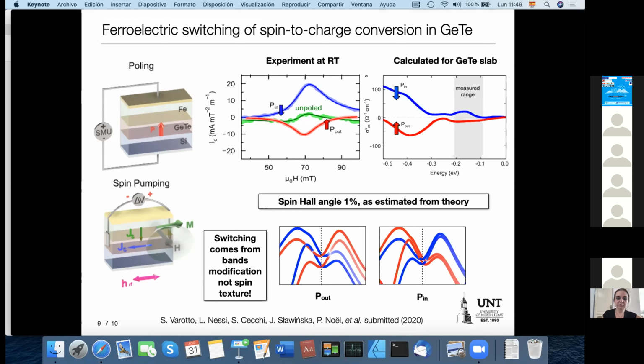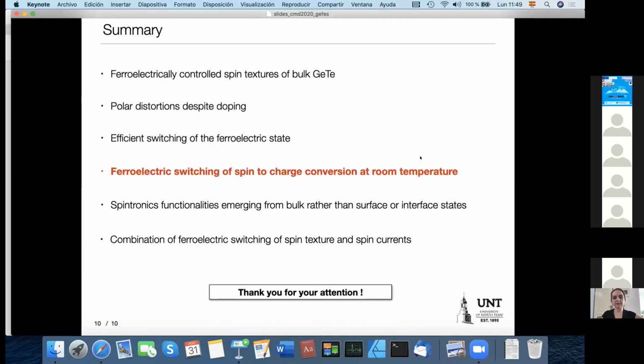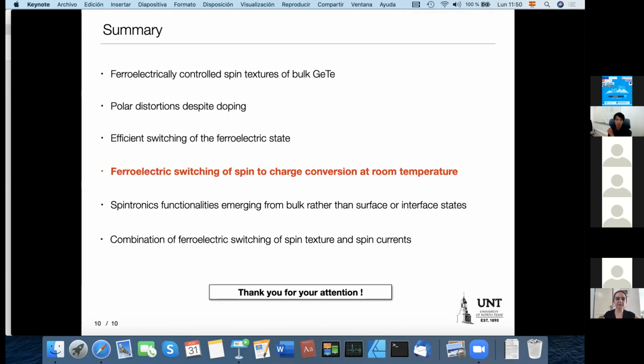Okay, so let me briefly summarize. I actually have shown the most important results in the last slide. So the ferroelectric switching of spin to charge conversion is really essential, and it can be done at room temperature. So it's promising for applications. Then another important thing is that this property emerges from the bulk, so we believe that it can be more robust in practice. And now we are trying to think about possible devices that can be designed based on these results.